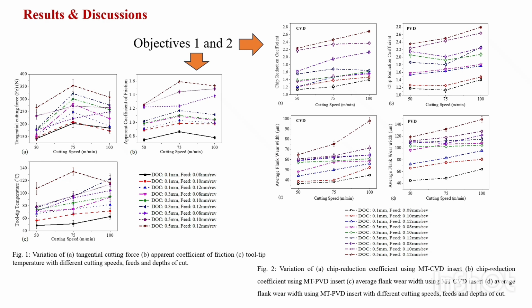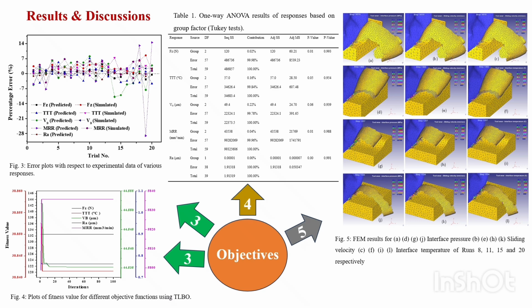Now objective 3, we can see percentage errors. The computed average absolute errors for all the responses except for MRR have remained below 5%, but for MRR, for a particular trial, it has reached high. But from the ANOVA analysis, it is seen that the R square value is almost 99.7% for the mentioned response, so the predicted model fitted well with the experimental data, we can say.